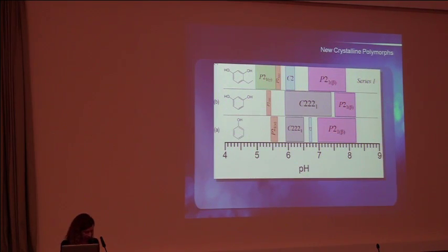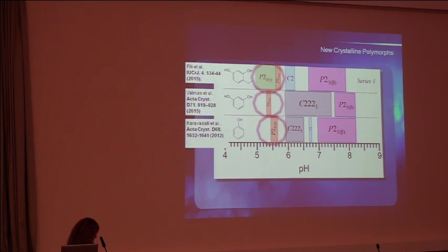To date, we have seen 2 new monoclinic polymorphs. The one is the one I just showed. We call it P21 gamma. And another monoclinic one is called alpha, in order to separate it from this one. They have the same space group but different lattice dimensions. And these 2 polymorphs appeared upon co-crystallization at acidic environment of insulin with phenol, resorcinol, or 4-hexylresorcinol.